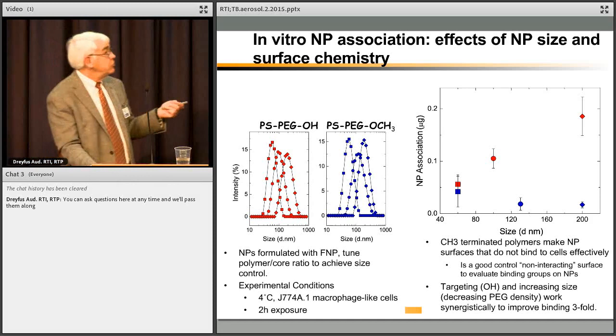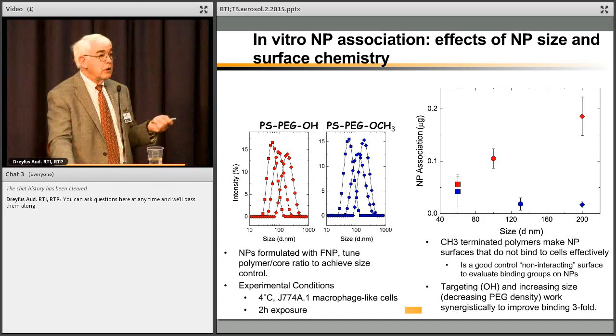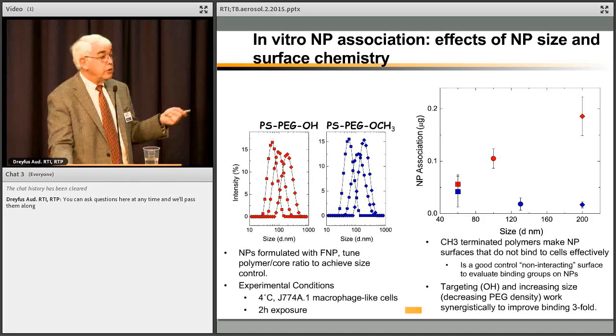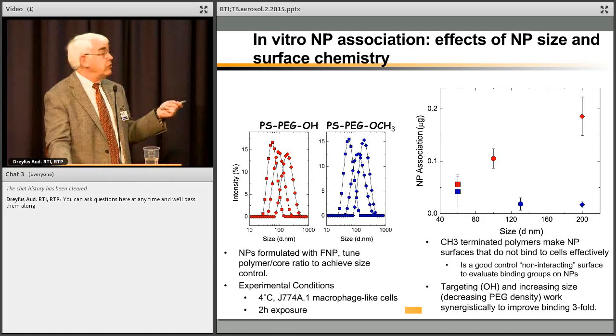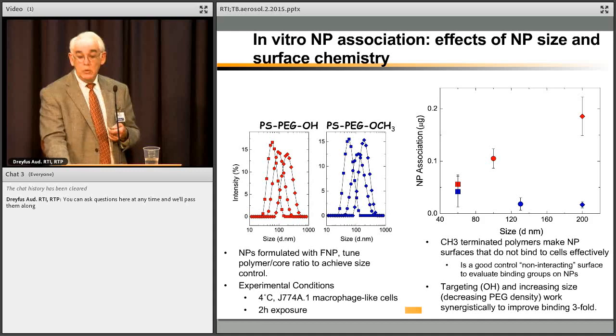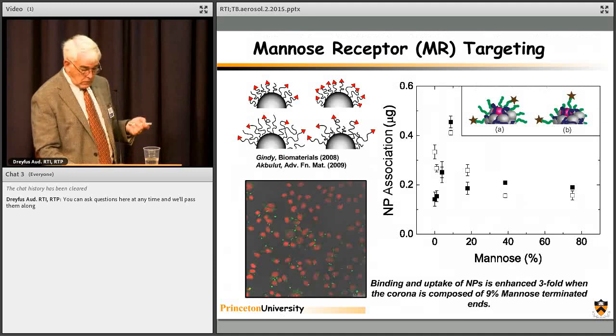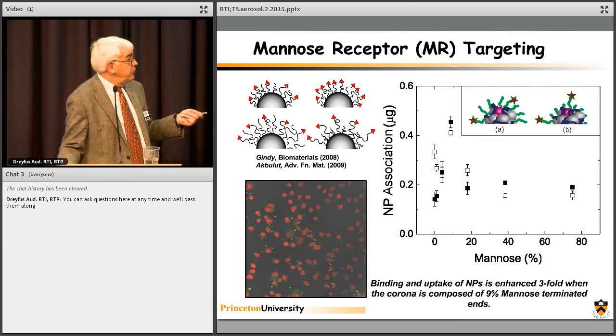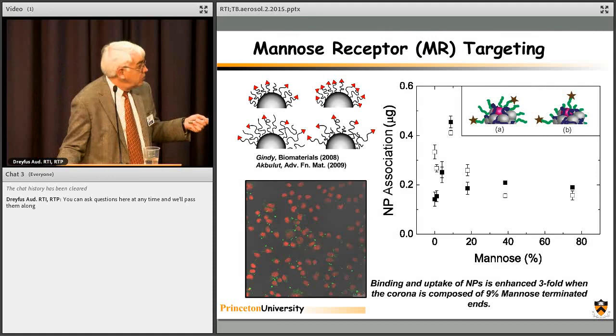Sure enough, here with methoxy, if we go to bigger particle size, the uptake into macrophages gets bigger and bigger as the particle gets bigger and bigger. The methoxy-coated ones are completely inert, so they are invisible, they're stealth material. So again, this shows small changes in the nanochemistry world or nanotoxicology world make huge differences in what happens to these things. So we're going to put methoxy groups on the PEG, and now what we're going to do is change the percent of the PEG which has mannose on it, starting with zero here, that's pure PEG, going up to 50% coverage there.